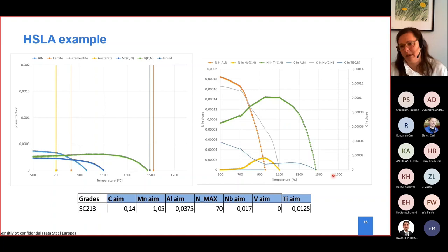It's only aluminium nitride, and it has only aluminium and nitrogen. Obvious. However, if we follow, for example, the titanium one, at the beginning this little guy likes to form mostly as a nitride. However, it has a part of it that will be a carbide. But when the niobium one appears, which on the opposite likes to form a carbide and not a nitride, it will fight together with